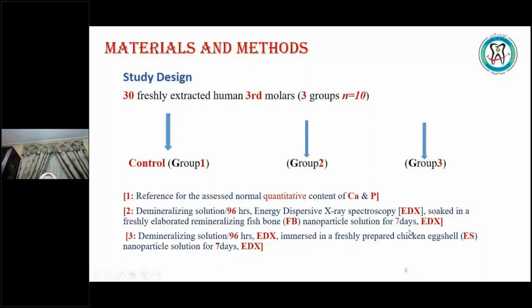Then it was soaked again in a freshly prepared remineralizing solution of fish bone nanoparticles for about 7 days. The third group was demineralized first, what we call artificial demineralization, which is the policy nowadays for researchers to assess the effect of a remineralizing solution. They do the demineralizing stage first to assess the effect of the recently innovated remineralizing solution using chicken eggshell for about 7 days.